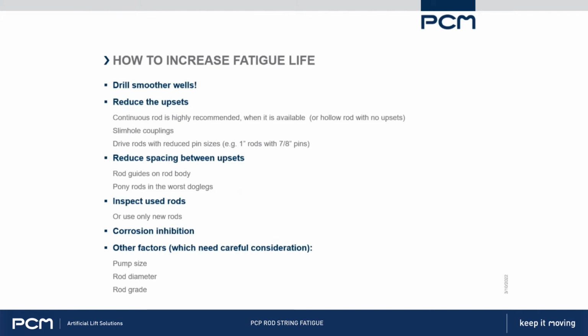The next step, if you can't use continuous rod, make sure you're using the smallest diameter couplings you can. Use slim hole couplings. I always recommend slim hole couplings, but I do recommend using high strength slim hole couplings to make sure you're not losing any torque capacity there.